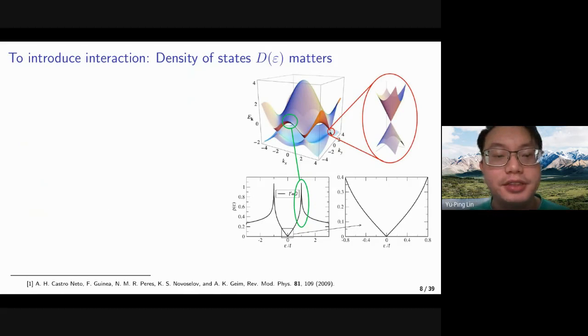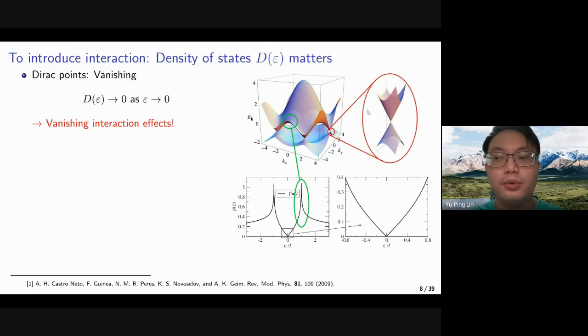So now let us try to introduce interactions to solid-state systems, or you can say to graphene. To introduce interaction, we know that we need to have some number of fermion modes on the Fermi surface so that they could interact. This means that the density of states at the Fermi surface will be important. If we look at the Dirac point, we'll find that the linear dispersion means that the Fermi surface vanishes at the Dirac point. And more rigorously, you can say that the density of states vanishes as the energy goes to zero, that is, as we approach the Dirac point. It means that we're having vanishing interaction effects.